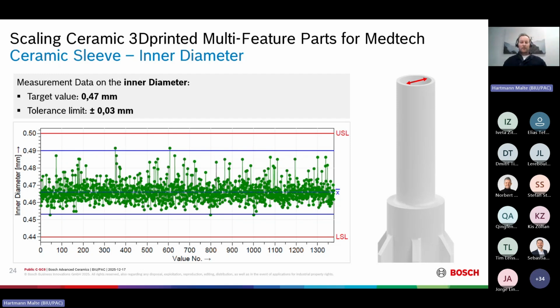5 parts of the 1,400 are outside of the process capability limits. And this is relevant because we see that there was still some work to do to achieve full process capability, and therefore reduced measurement effort. In this case, this would mean that we could just random sample test those parts. However, the values are spreading to bigger size due to instability of the green part. And here additional effects are a closed cavity and of course, the necessary cleaning procedure.